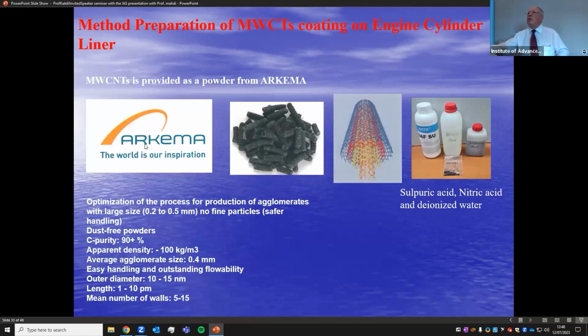Now also we tried, surprisingly, this is also a PhD thesis of my student. He's working very hard. He is good. We tried also with multiwall carbon tubes. Just before coming here, a month ago, we started, almost 2 months. So we bought multiwall carbon tubes from Arkema, and you see the specification. But the solution is different. We found the recipe, the article, and we need sulfuric acid, nitric acid, and deionized water. Then you can do coating with those ones.